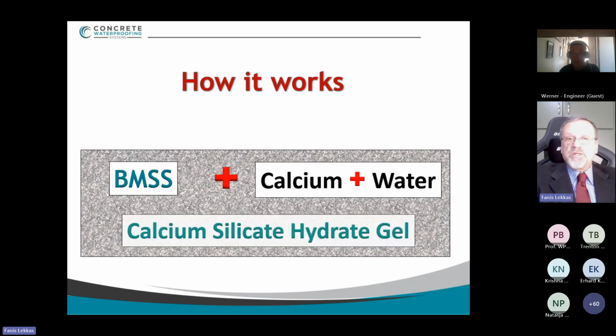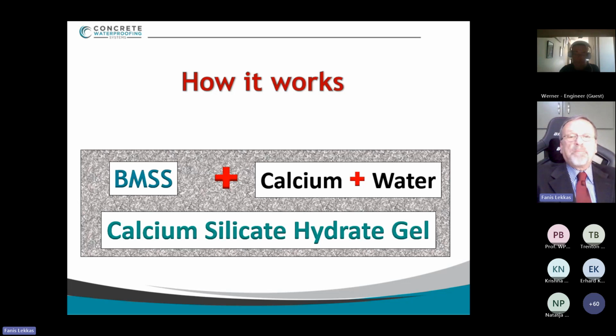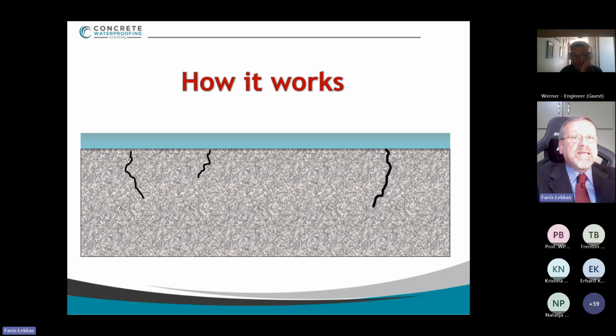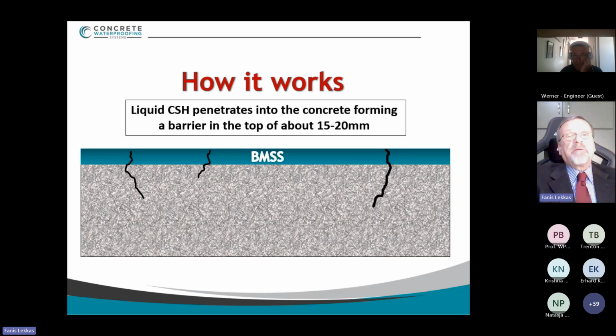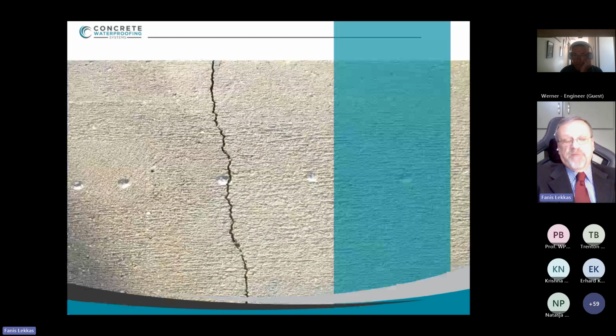It reacts with the calcium, which is already in the concrete, and with simple water that we add by watering the applied area on the day of application, on the second day, and on the third day. And it creates an insoluble calcium silicate hydrate gel. It has the same structure as concrete, which is essentially a calcium silicate hydration product. What it does is that it seals the porosity and the capillarity of the concrete on the top. It seals static cracks which are already in the concrete, and this is all happening inside the concrete and not on top of the surface.